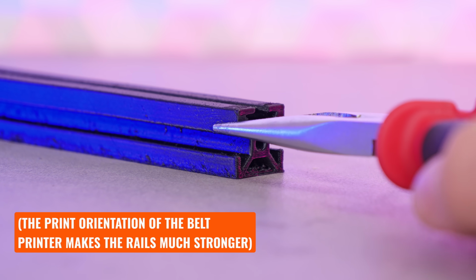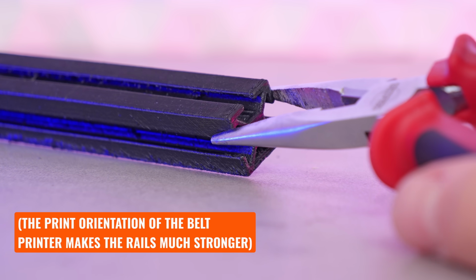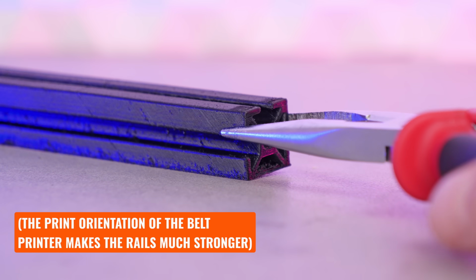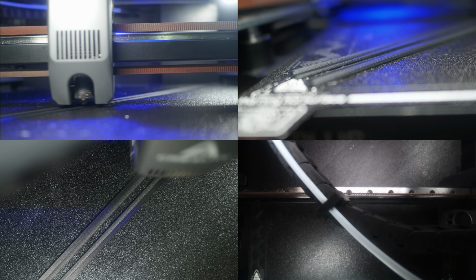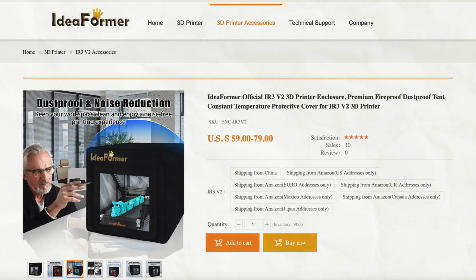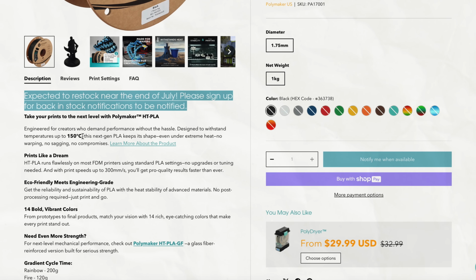But honestly, looking at some of the samples that I printed in plain old ASA, I think that the slots on those actually might be stronger. And that makes sense since additives do add rigidity, but they compromise layer adhesion. I think that in order for this to work, you really need to give the material the ideal conditions for layer adhesion. So I'd be interested to retry printing these in an enclosed printer in ASA or even PPA-CF once I enclose either the belt printer or the Sovol SV08 Max. Or maybe one of you wants to experiment with printing these on Polymaker's new HT PLA, which despite being printable on an open printer, should be really rigid and withstand, obviously, the temperatures we need for most purposes.